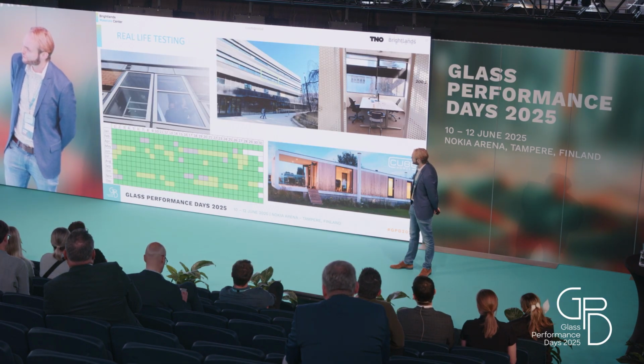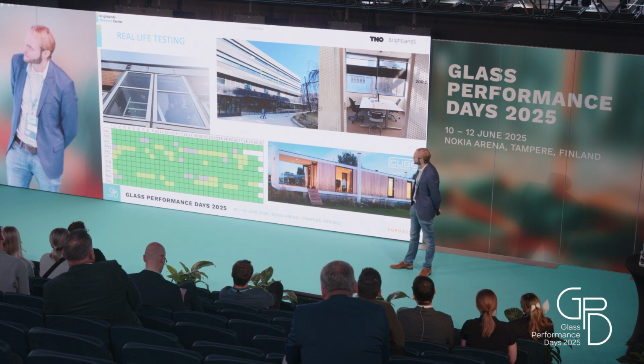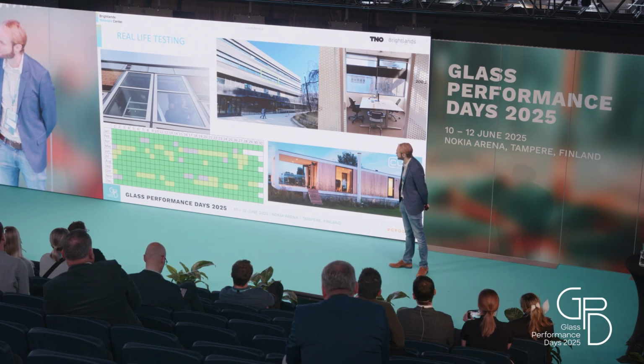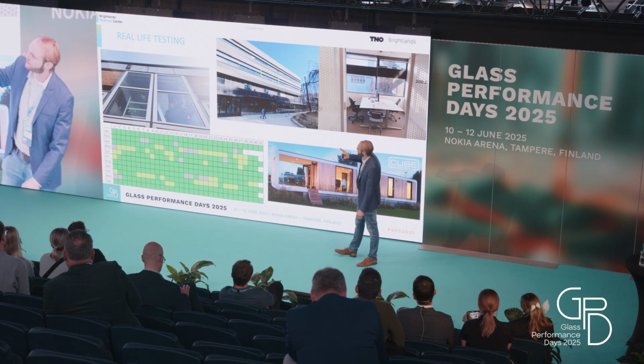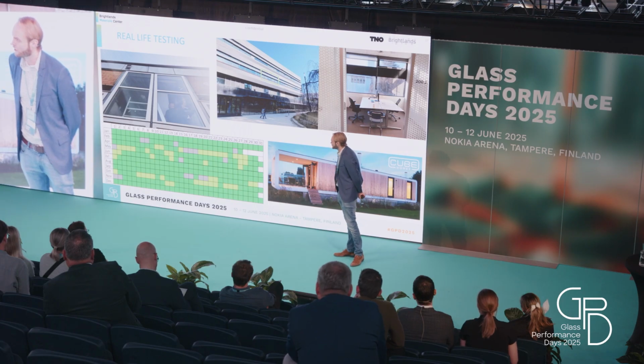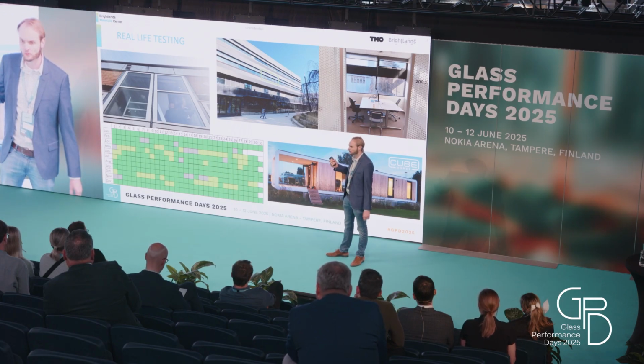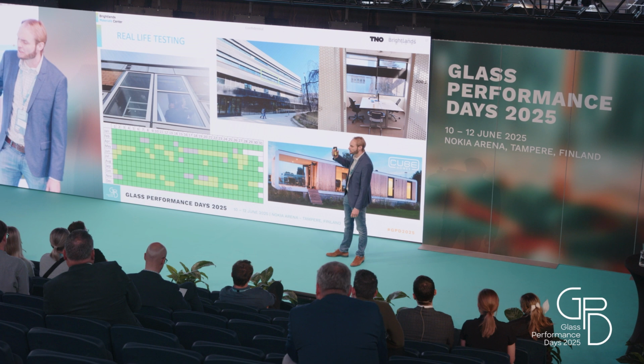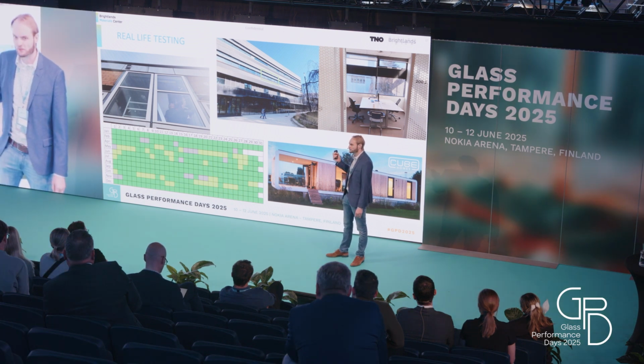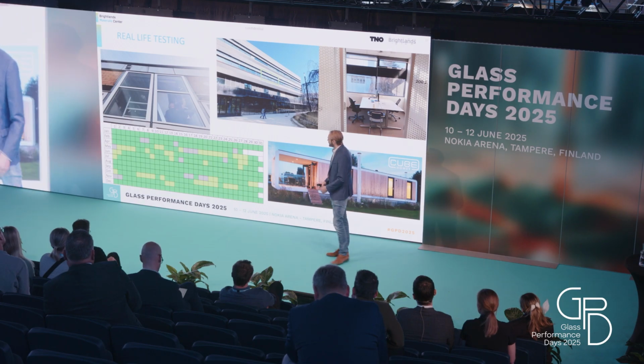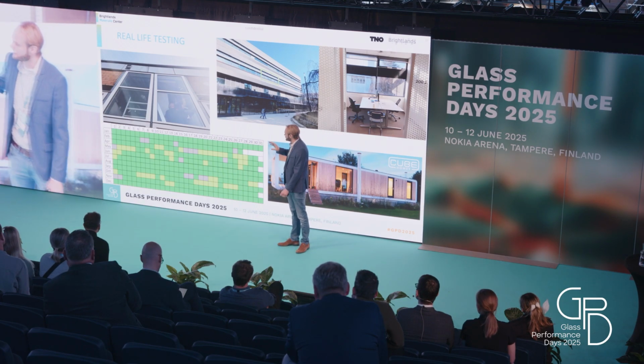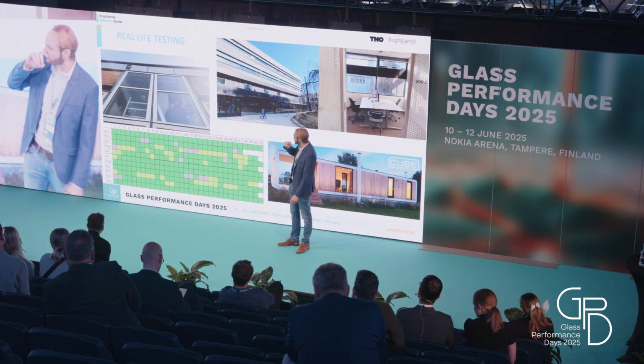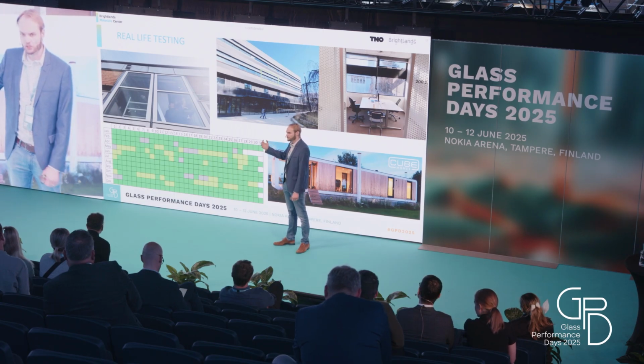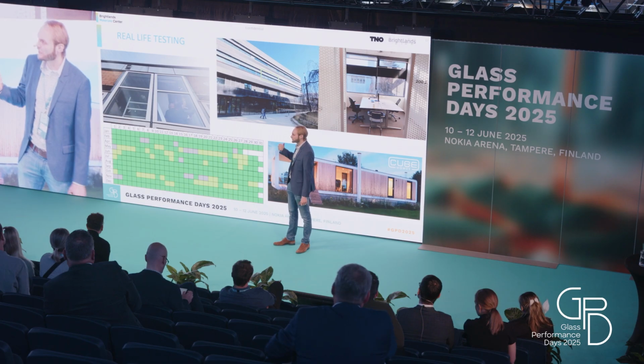The next thing we have also been doing and are still continuing is real-life testing. So we installed some of these windows in a test facility in Eindhoven, where we monitored the performance of the window in combination with the temperature of the glass, because the material switches its properties based on the external glass temperature. And here, in the first investigation, we were looking at when the material transitions, and at what glass temperature and at what outside temperature.